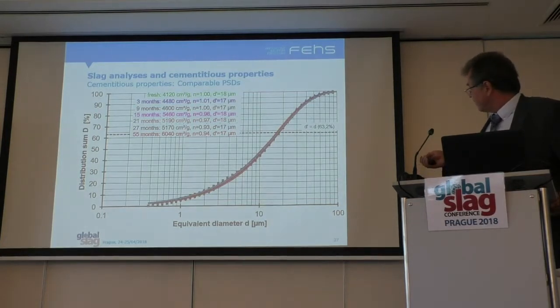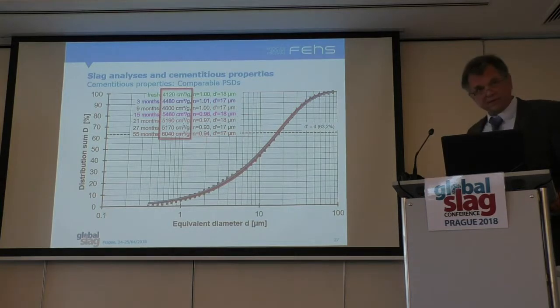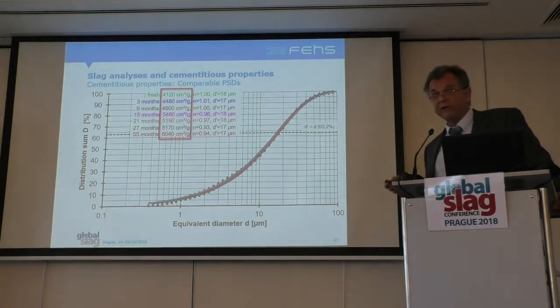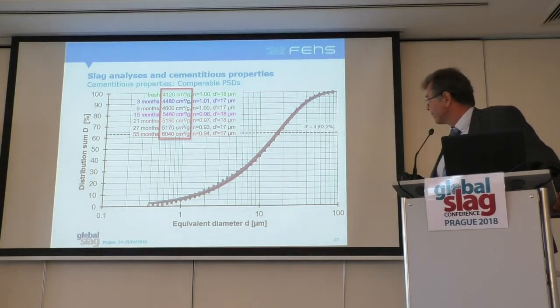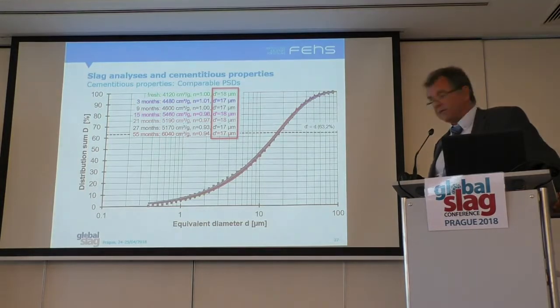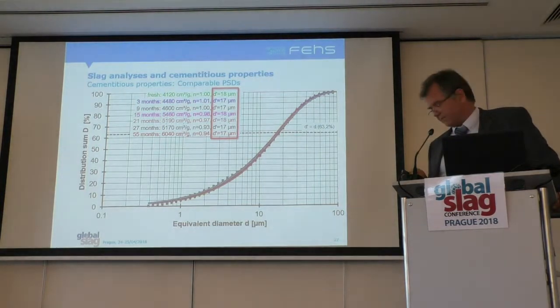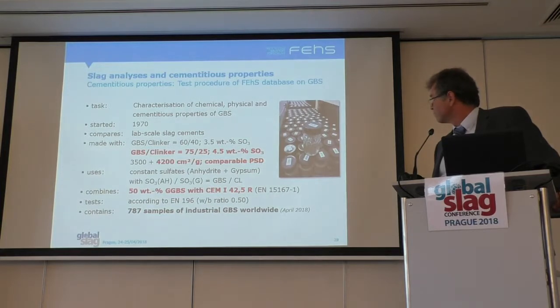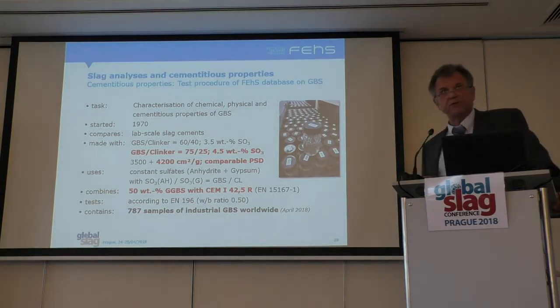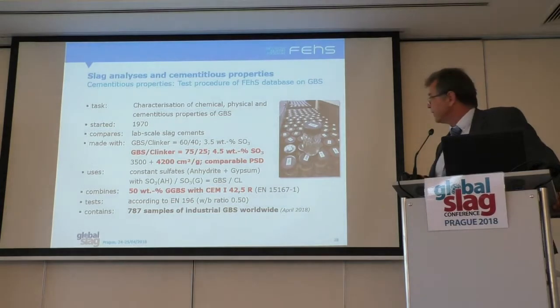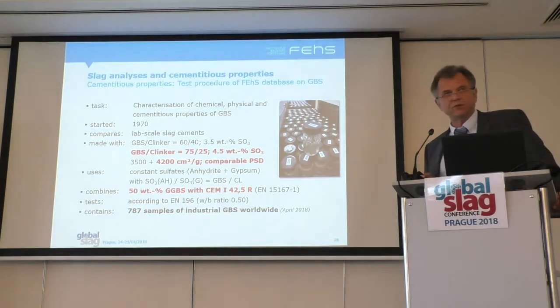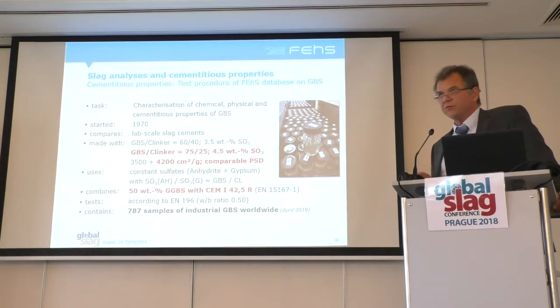In fact, we have a very similar particle size distribution, but very, very different Blaine values. But we ignored the Blaine values. For us, it is important to have the same PSD. The ground material we took and investigated the cementitious properties according to a procedure which was introduced in our institute in 1970 in order to characterize any GBS from somewhere.